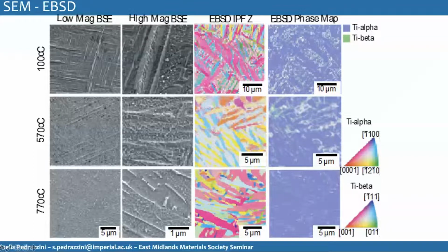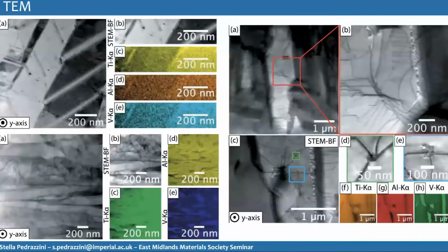Looking at the texture with EBSD, there was a substantial change in texture. The amount of alpha and beta, most of these are alpha. When we phase mapped, we could detect some beta phase in all of them, so maybe it was not enough for the XRD to pick it up, but the EBSD certainly did. But what was extra interesting is the picture at the top left, the sample at 100. I'm pointing at it with the cursor, and it's very heavily twinned, this sample. This is a TEM sample, electropolished, and all of them were cut in the same direction, which is perpendicular to the printing direction.